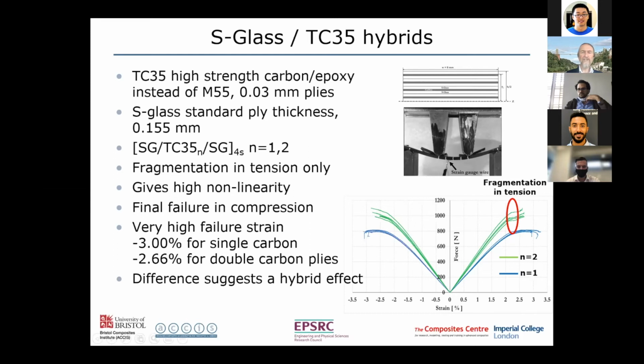We get fragmentation on the tension side, and you can see that gives a substantial change in the slope, and we get these quite high strains, and final failure by compression. But look at the strains here. 3% strain is a very, very high failure strain for a carbon fibre material. That's 2 or 3 times what you typically expect for this sort of material in normal direct compression. And that's for several reasons.